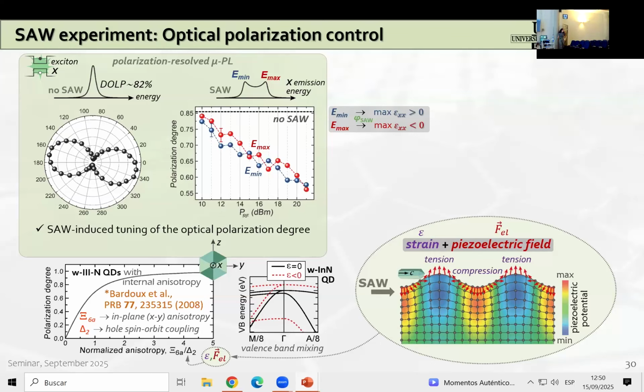Now, there is a theoretical prediction made by other authors, which basically shows that in nitride wurtzite quantum dots with internal anisotropy, any change in spin-orbit coupling, or basically in valence band mixing, can lead to a significant change in the polarization degree, as you can see here. And this change can be obtained by applying externally either strain or electric field, such as that of our surface acoustic wave. So basically, either strain or piezoelectric field, or both, of our propagating acoustic wave can be responsible for this reduction of the polarization degree.